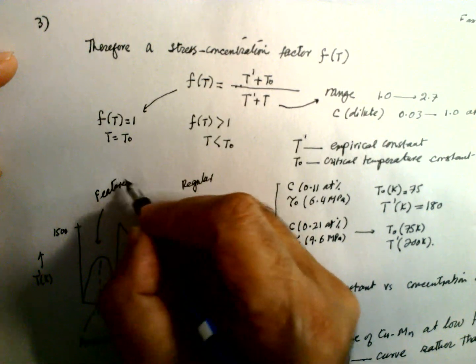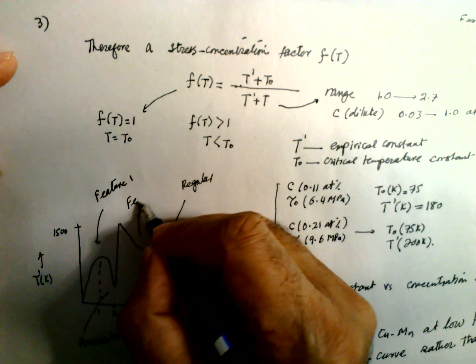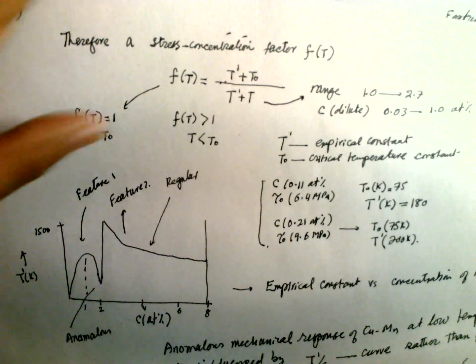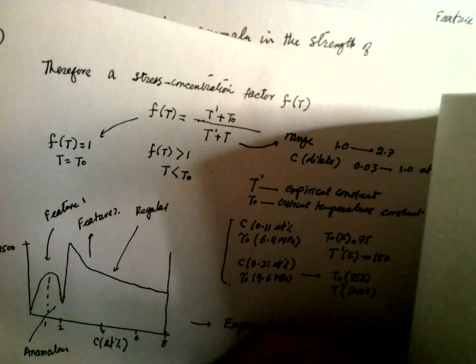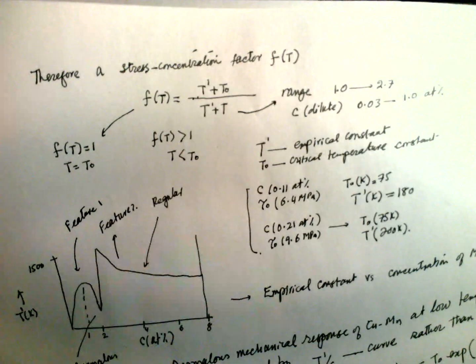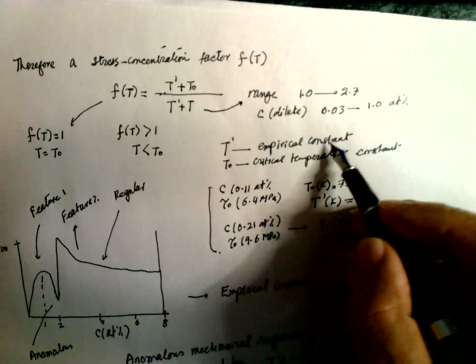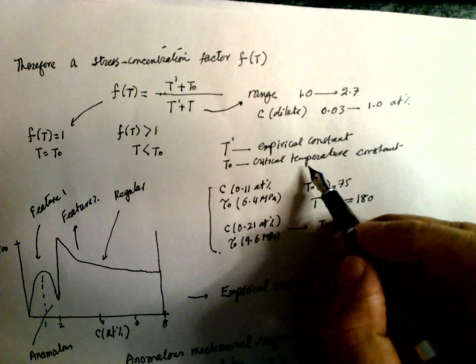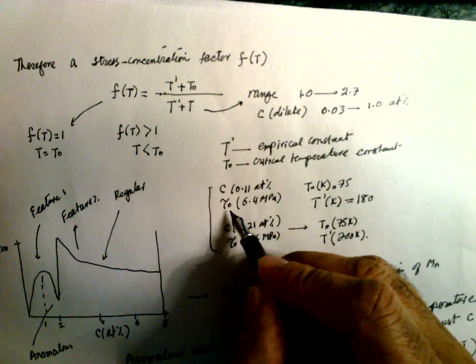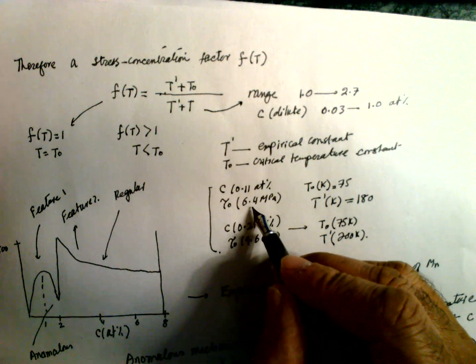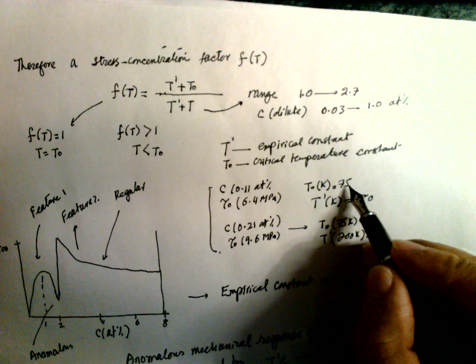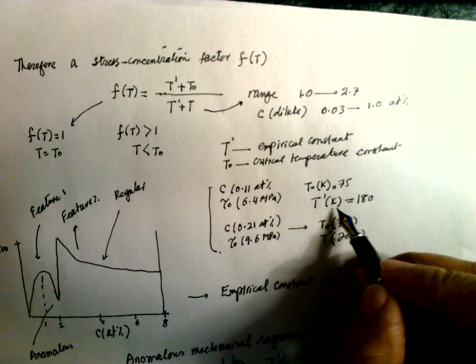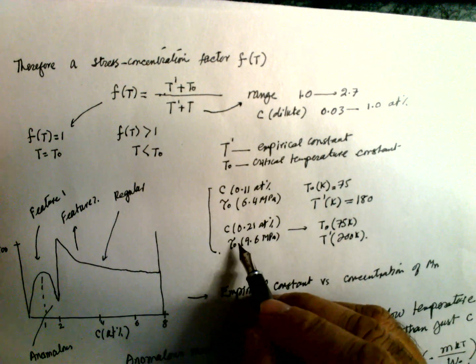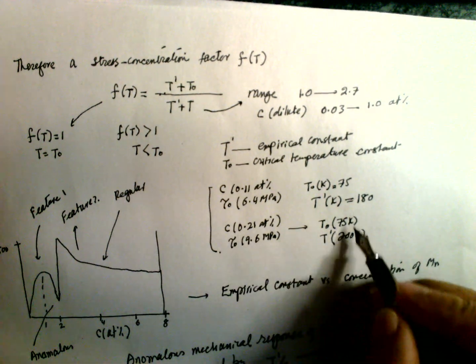So this is feature 1, and this is feature 2, which I have explained to you. There are two curves: feature 1 and feature 2. T empirical is a constant, and T naught is a critical temperature. When C is below this and tau naught is 6.4, T is 75 Kelvin, and T empirical is 180 Kelvin. Similarly, another one is 0.2, and there is a variation of this one.